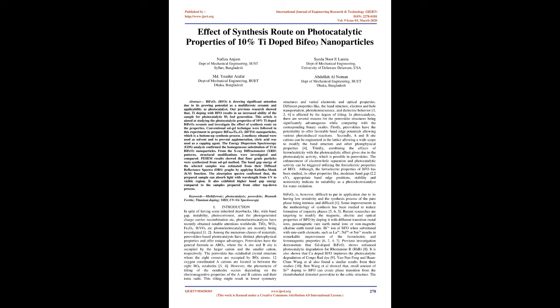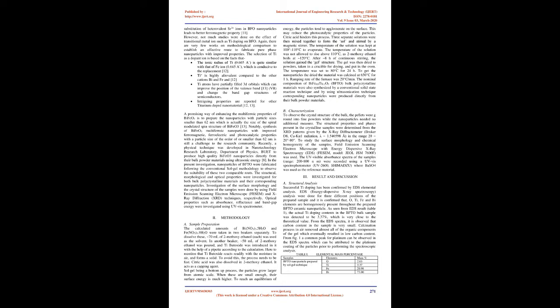In photocatalysis, there are several reasons for the perovskite structures being significantly advantageous compared with the corresponding binary oxides. Firstly, perovskites have the potential to offer favorable band edge potentials allowing various photo-induced reactions. Secondly, A and B site cations can be engineered in the lattice allowing a wide scope to modify the band structure and other photophysical properties. 4. Thirdly, combining the effects of ferroelectricity with the photocatalytic effect gives rise to enhanced photocatalytic activity, which is possible in perovskites. The enhancement of electron-hole separation and photocatalytic activity can be triggered utilizing the ferroelectric properties of BFO.